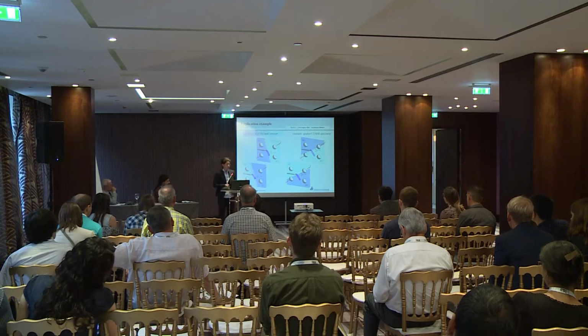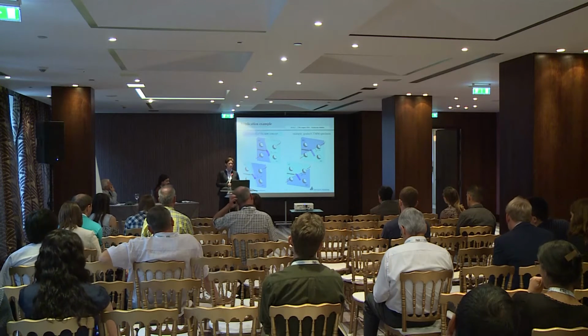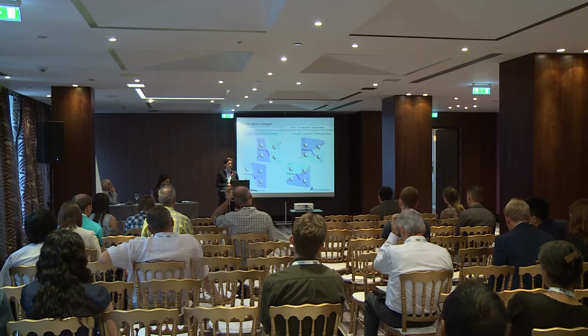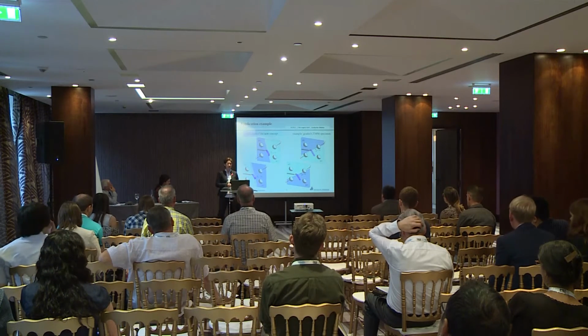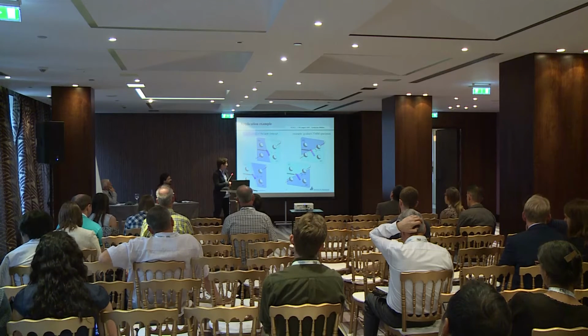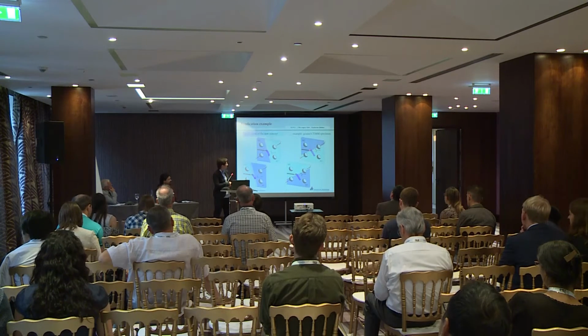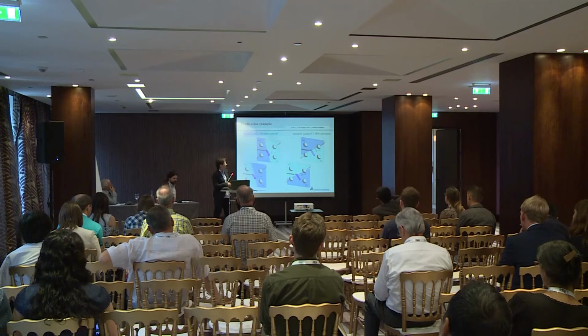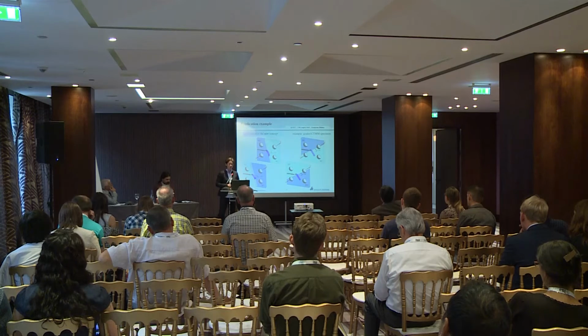So the aim of this is that you have to look not only at the stress occurring at the crack front, but you also have to take into account the local material property areas, as well as kinking angles, what I mean is the local kinking. So for this transition area, obviously it won't be 30 degrees because the crack already had kinking, so this grading now would be around about 90 degrees. So that's a big influence on the crack path as well.